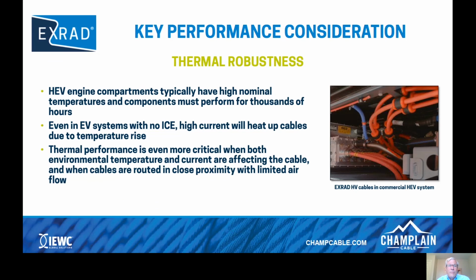Thermal robustness is also very important. HEV engine compartments typically have high nominal temperatures, and the components must perform for thousands of hours. And typically when you think about an EV, you don't think there might be high temperature, but in fact there is. And there's little airflow. So even in EV systems with no internal combustion engine, high current will heat up the cables due to temperature rise. Now, this is an important feature that many EV manufacturers have taken advantage of with high current insulation and high voltage cables. If an insulation can withstand a higher temperature, they can pump more current through, raising the temperature of the conductor, but not damaging the insulation.